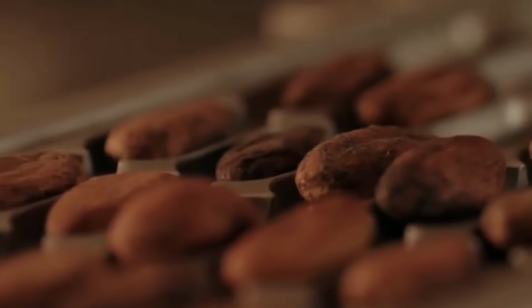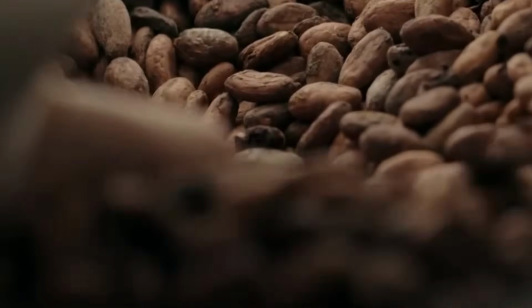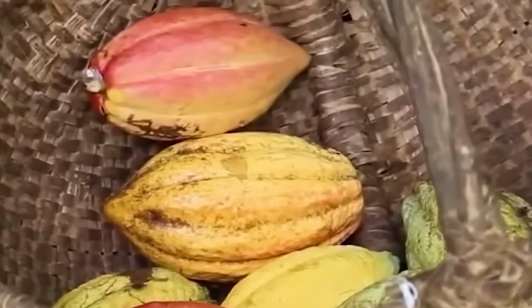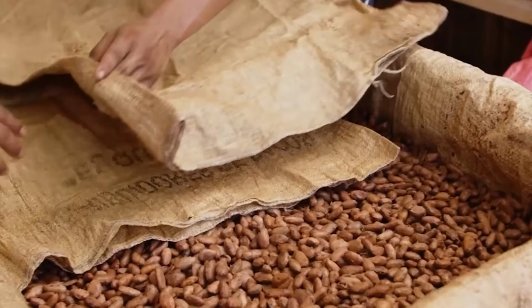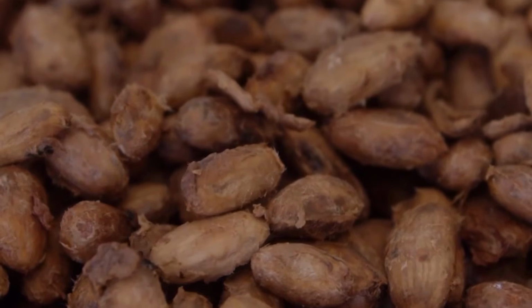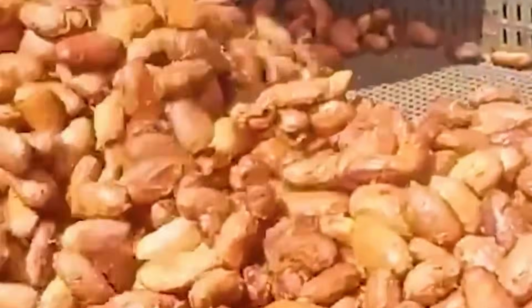From these silos, the beans are measured out by weight and directed into a cleaning unit where vibrating screens, air classifiers, and magnetic separators remove stones, dust, string, and any foreign matter, so that only clean beans proceed to the next step. The cleaned cocoa beans are then transferred to a batch roaster or continuous drum roaster, which exposes them to dry hot air with precise temperature control and rotation speed to ensure the beans are heated evenly from all sides. Roasting develops the flavor of the cocoa, reduces astringency, and darkens the color of the nibs inside the shell.